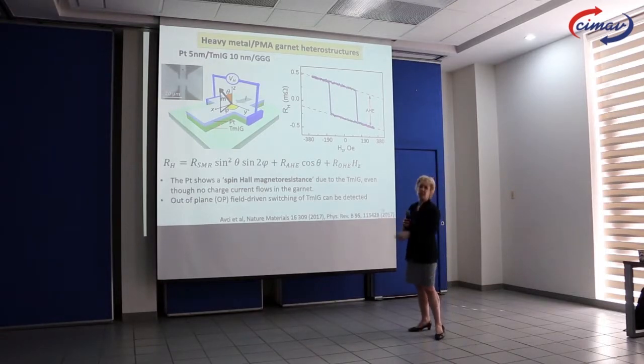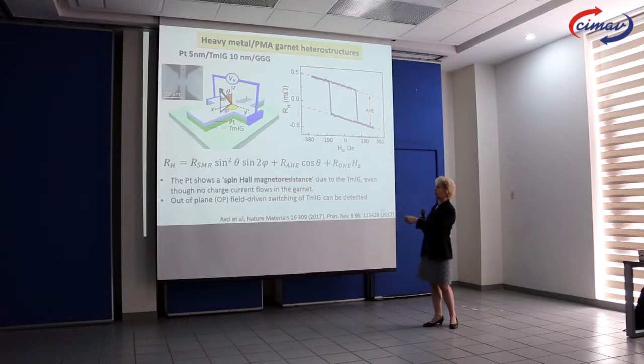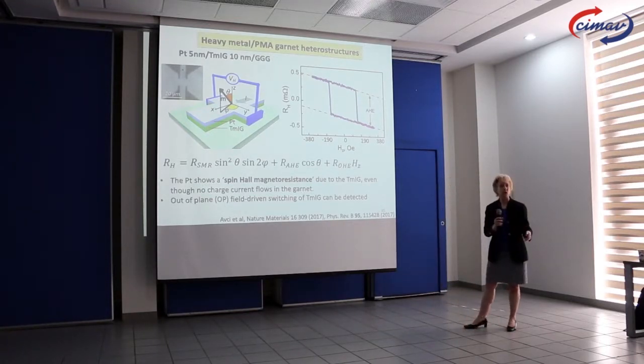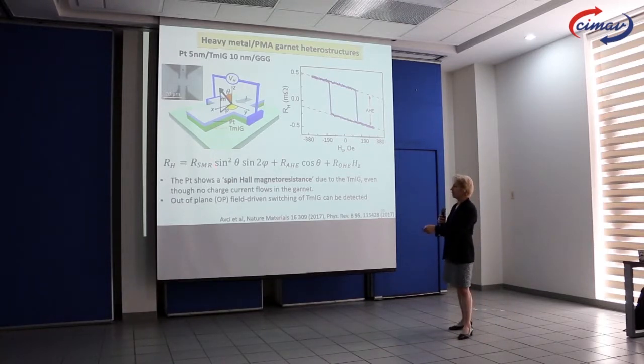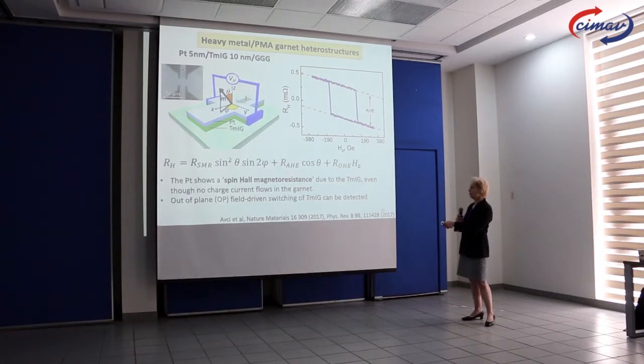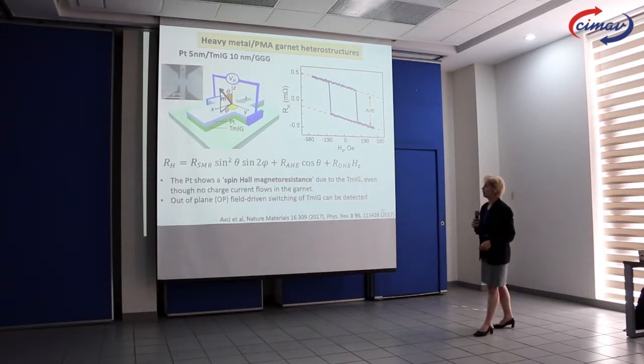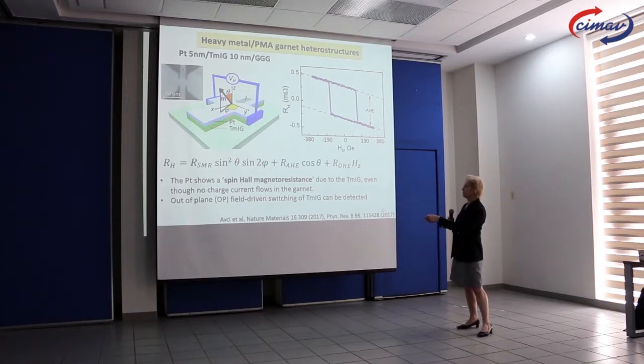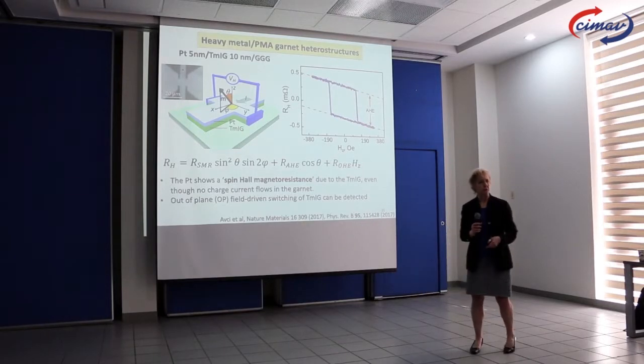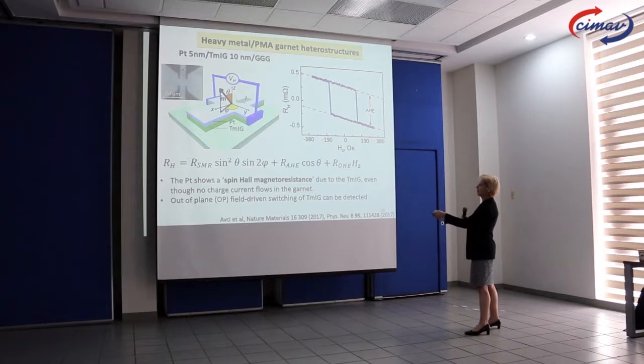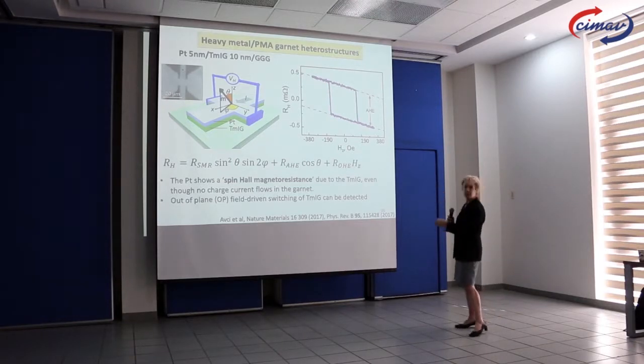But because the platinum is on top of a magnet, and there's a spin current which flows from the platinum into the garnet, and then interacts with the garnet, and then gets transmitted back into the platinum, we also get a contribution to the Hall effect from that magnetic interaction. And it's called the SMR, the spin Hall magnetoresistance. And we will also see an anomalous Hall effect, because when the garnet changes direction of magnetization, we'll get an abrupt change in the Hall voltage of the platinum. And these things have different angular dependencies on the in-plane angle and the out-of-plane angle. So we can separate them out by doing various angular measurements, which I won't bore you with, but just for this case, if you apply an out-of-plane field and switch the magnetization of the garnet, you can see a step in the platinum resistance. So you can see when it switches.